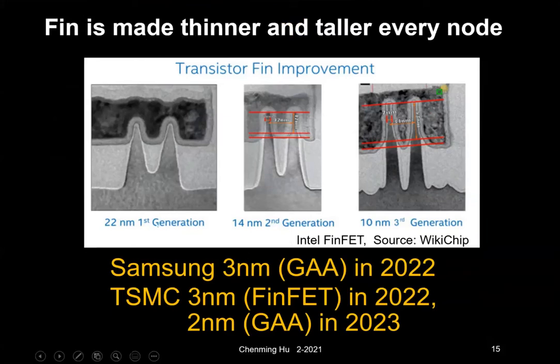So as a result, the fin has been made thinner and taller every node. Now this again is a collection of Intel's FinFET, the first generation 22 nanometer, and look at the 14 nanometer, thinner and taller. At 10 nanometer, it's 7 nanometer thin and 55 nanometer tall. So when this cannot be made thinner and taller, then people will go to the GAA, turn it around.